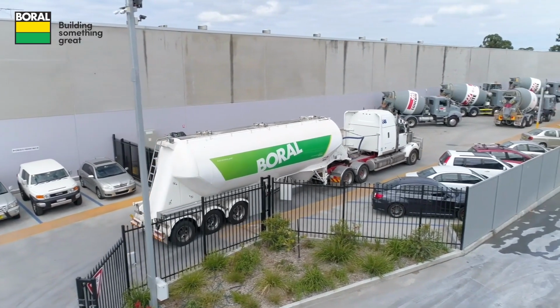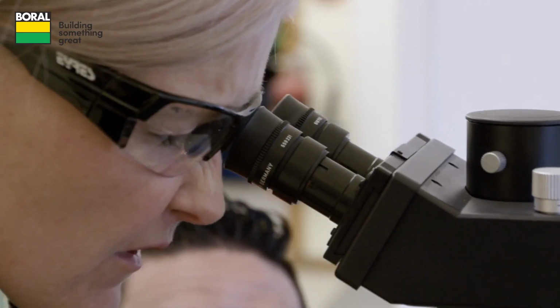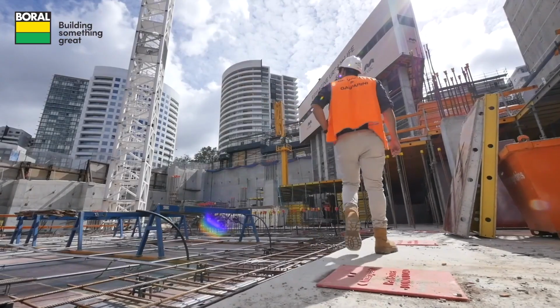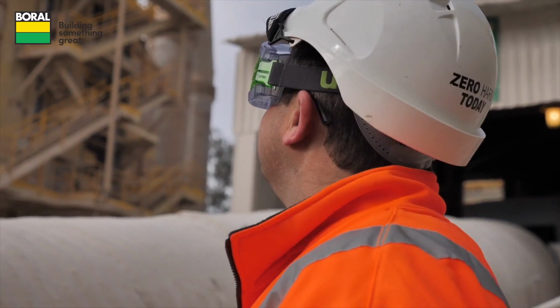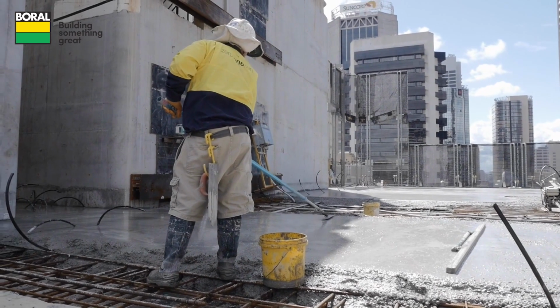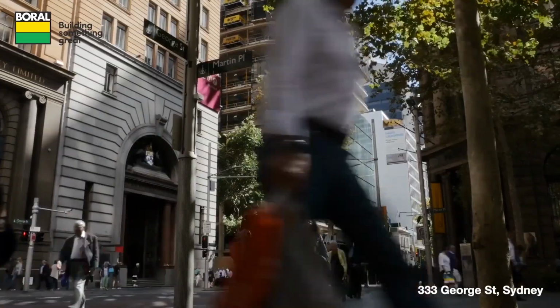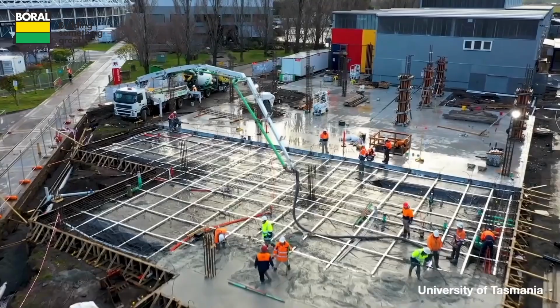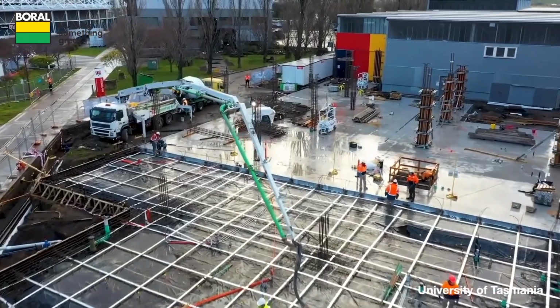This is the challenge that we took on years ago, and that's how our Envisia product was born. Envisia is a unique lower carbon concrete product that offers more than 50% reduction in the cement content of concrete. But more importantly, it does that not only without compromising the early age strength of concrete, but also by offering improvements in several key durability properties of concrete. For example, Envisia has excellent resistance to chloride ingress and significantly lower drying shrinkage than normal concrete.